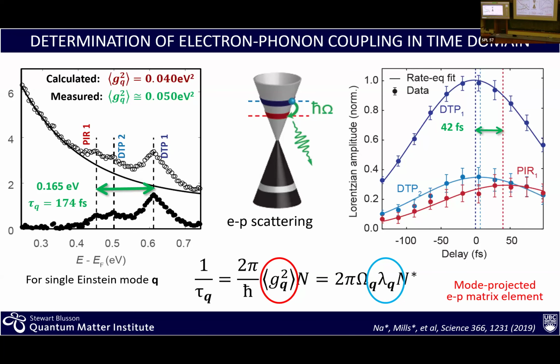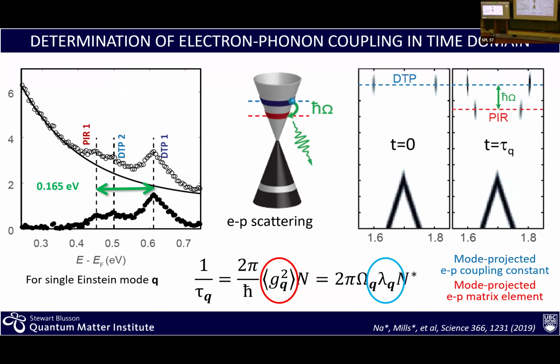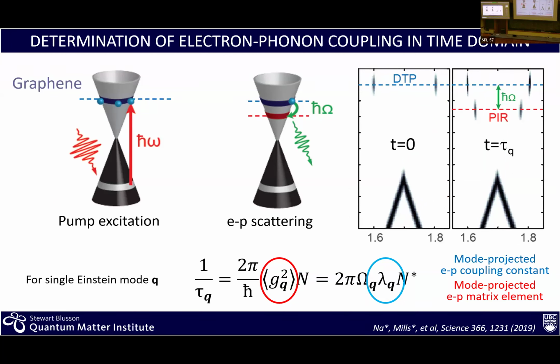In principle, one could change the excitation energy to scan along that cone, and as I scan along the cone, not only the K changes, also the Q changes. And so that's basically what we would like to do. This particular experiment was done with the fundamental photon energy we get out of our oscillator. Now we have an OPA, an optical parametric amplifier, so we can change the photon energy also for the pump. And the idea is to really do that. I think all of these techniques are great, and they all provide one complementary view on the problem. This particular case works extremely well because of a limited band structure. If you were to go to a much more complicated band structure, then it gets more challenging.